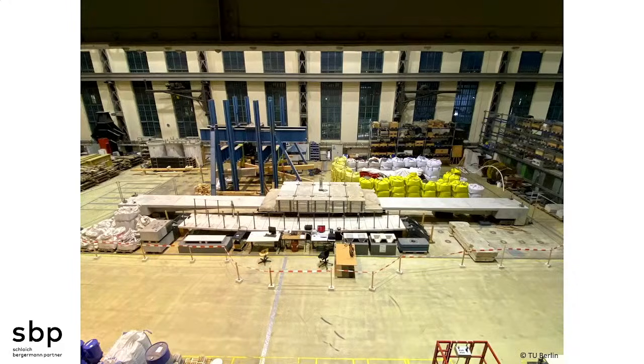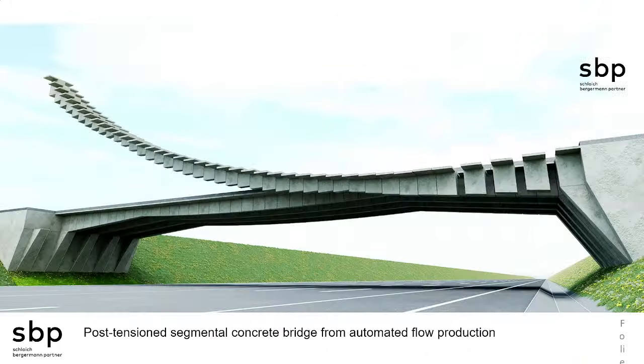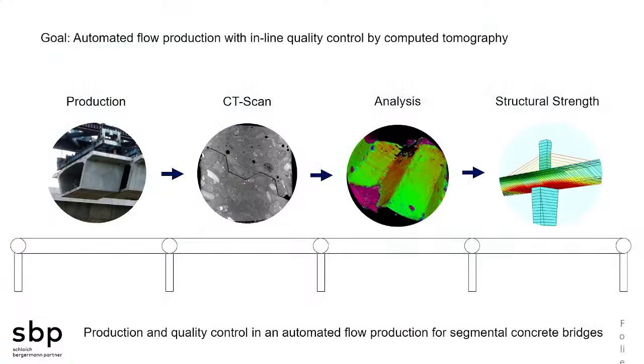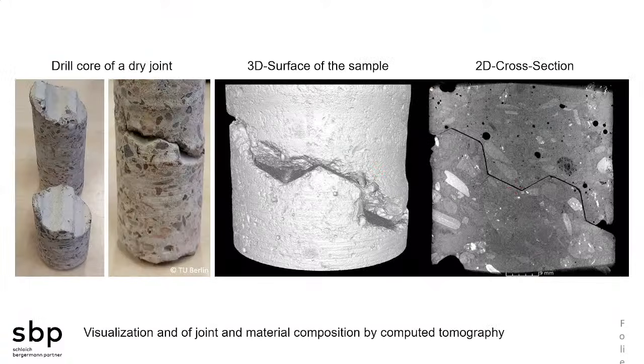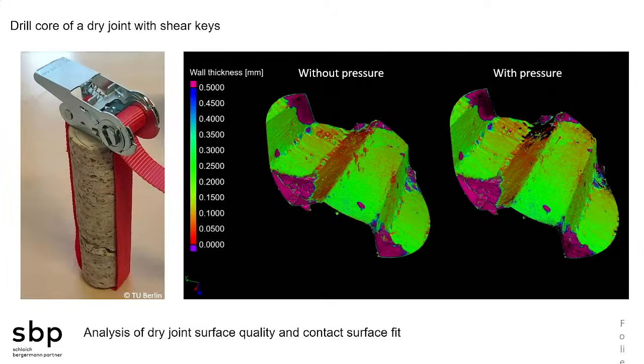And we have loaded it very heavily, as you can see here. Then with a shaker on top, we did 2 million cycles, and we found out there are no fatigue issues in carbon fiber. And we are now trying to do this with small elements. We do computer tomography to see what the joints say to that. If you do computer tomography, you see all the little cracks in the concrete. We can check the surface and how the surfaces are connected.